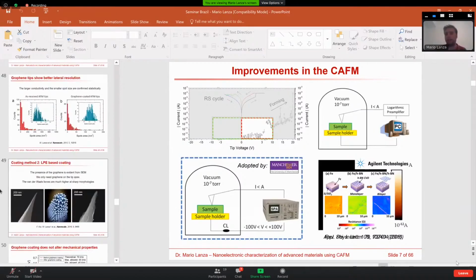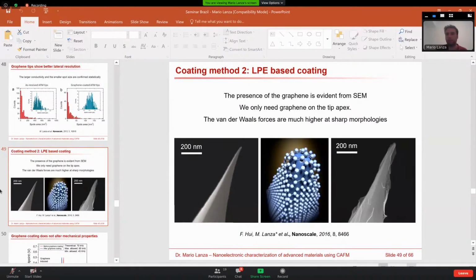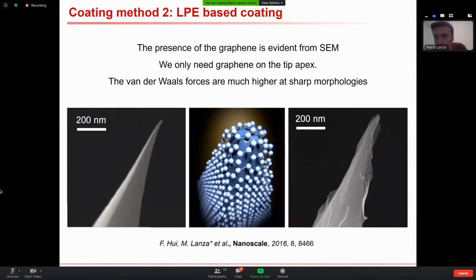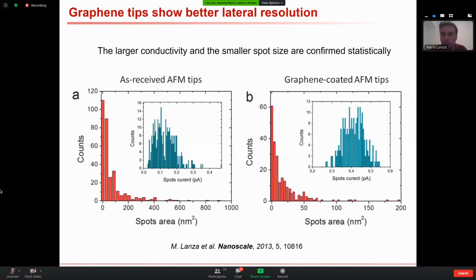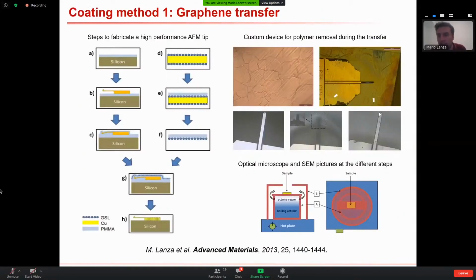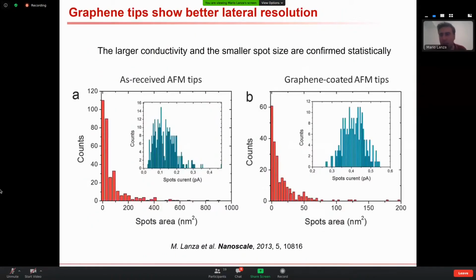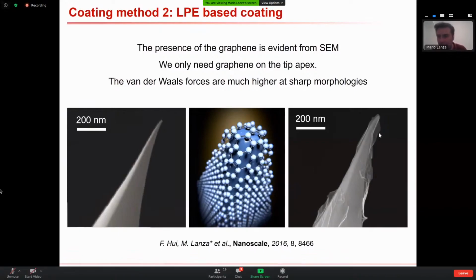Yes, that is a very excellent question. In the image on the right, you can see very well that the graphene is coating the apex of the tip. I have to say something: we are putting a tip that is on a chip. You can see the chip of the AFM tip here. This is a cantilever containing the tip, and this cantilever is attached to a large chip. This chip you can take with the tweezers. So when you have the solution containing the graphene, you immerse the tip with the tweezers and take it out. What you get is what you see in this image.